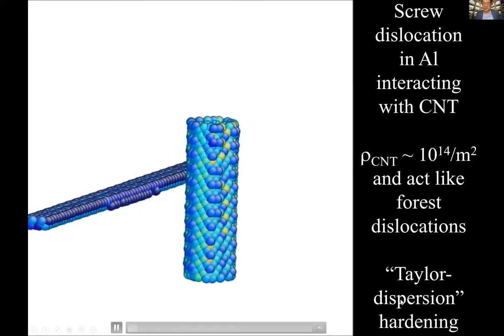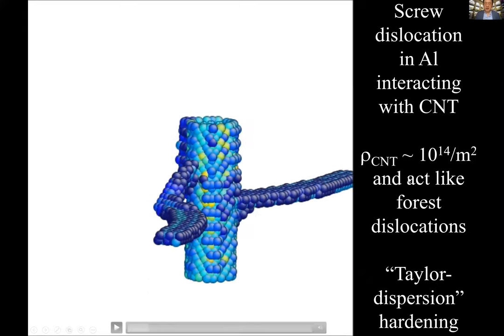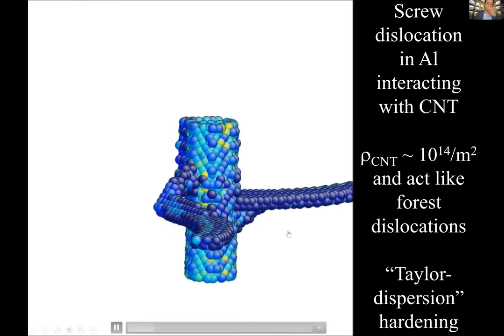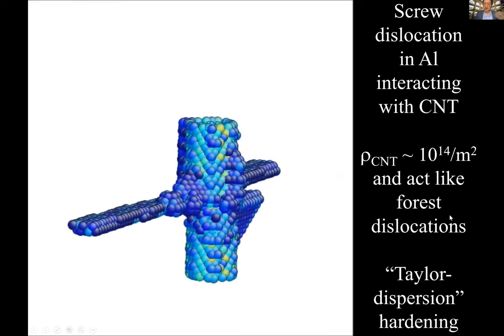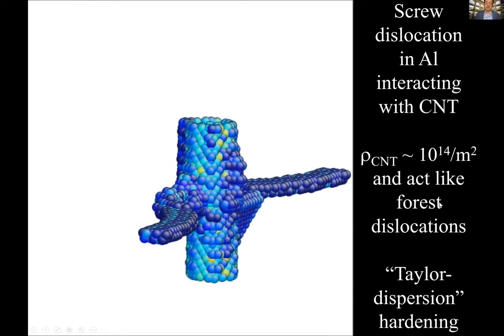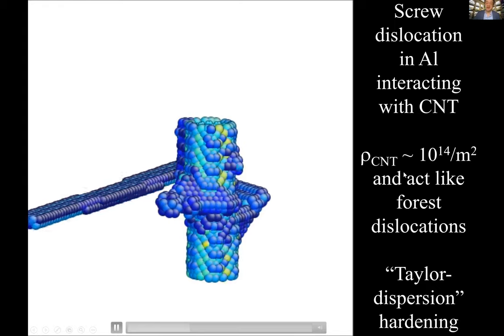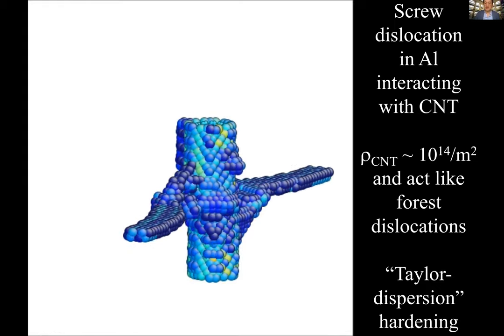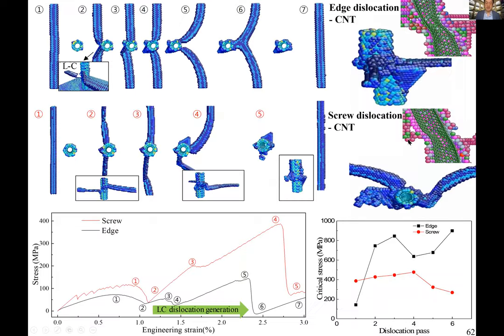So like I said, we actually give a name for this hardening. When we compute the total length of carbon nanotubes, when you have a good dispersion at one volume percent, it's on the order of 10 to the 14 per meter squared, which is similar to the forest dislocation density in a medium work hardened material. So this is a trick. In terms of hardening, it's like a forest hardening, which we know is a good hardening mechanism, and doesn't embrittle the material as much as, let's say, the Hall-Petch relation. And that's why we think it maintains the ductility.